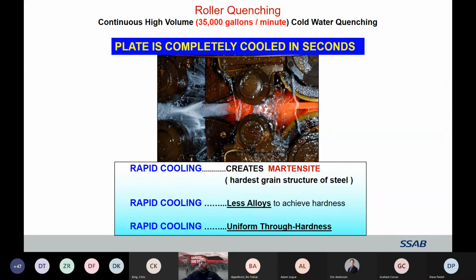Now what this does is it creates a martensite structure throughout the steel. It also has a very consistent grain structure. We need fewer alloys to achieve the hardness, and this also helps us to have a uniform through hardness. So like we were talking about earlier, the through thickness hardness of that plate is very consistent, very even.